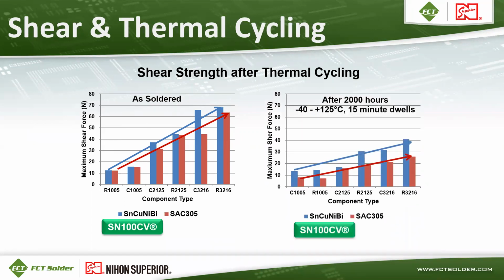After thermal cycling, 2000 hours, -40 to +125C, the shear force drops dramatically for both alloys, but the SN100CV still maintains a higher shear force than SAC305, which drops off a little more dramatically.